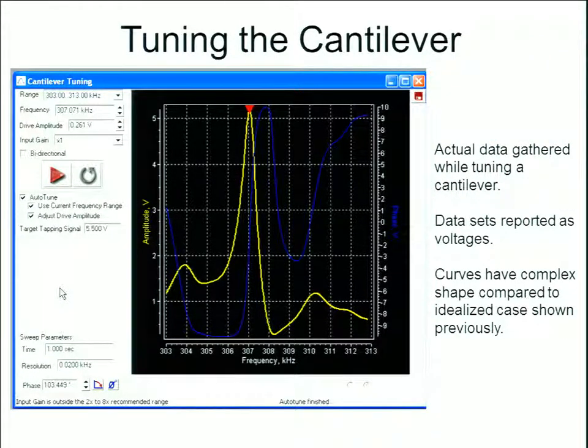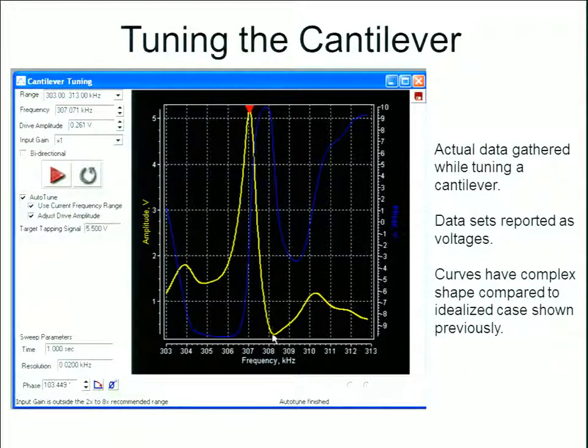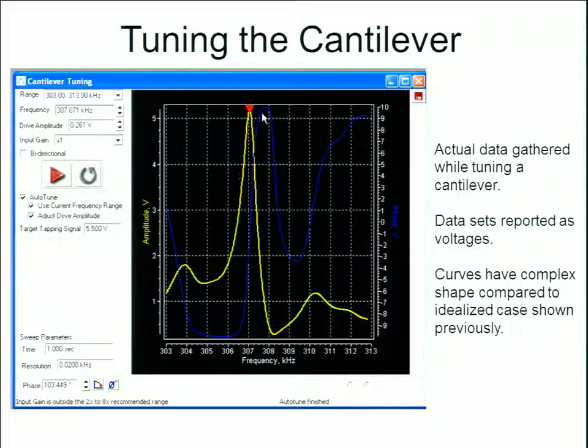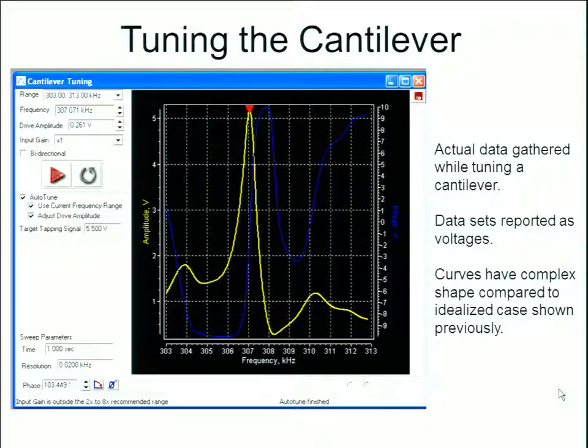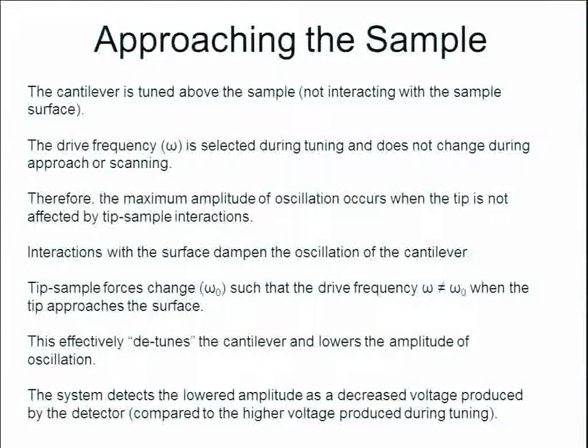Here's an actual image from the software — a more accurate representation of what your amplitude looks like when driving the cantilever at different frequencies. When we tune a cantilever in free space, you get a peak amplitude. This one happens to be at about 307,000 Hz.